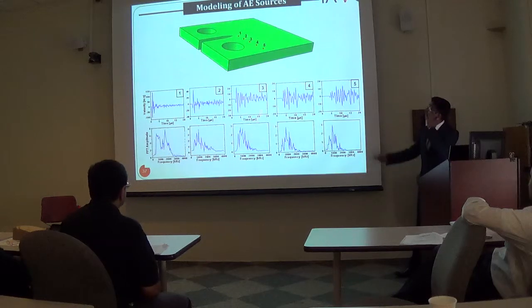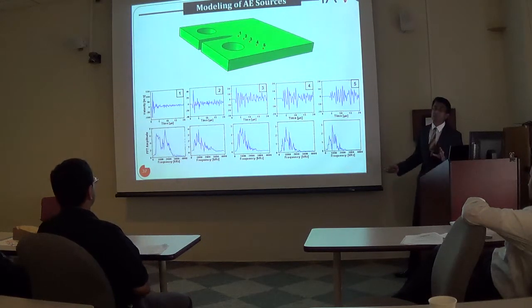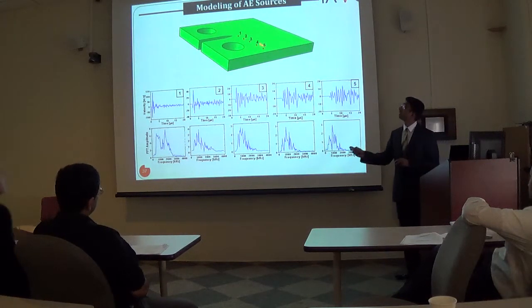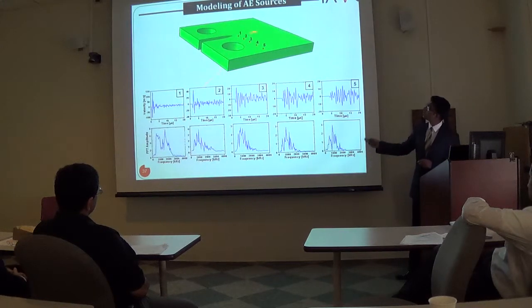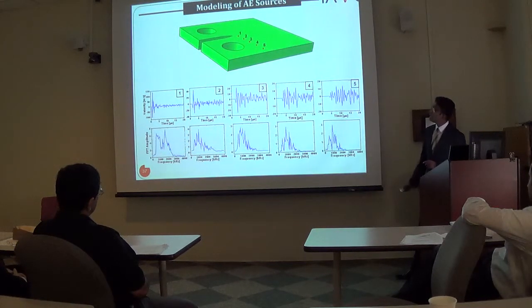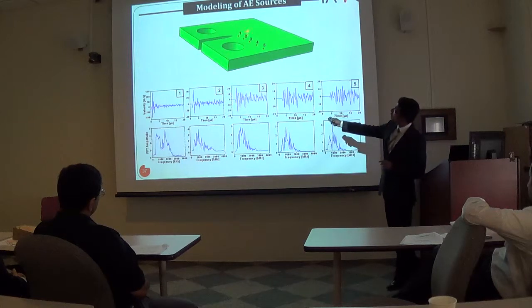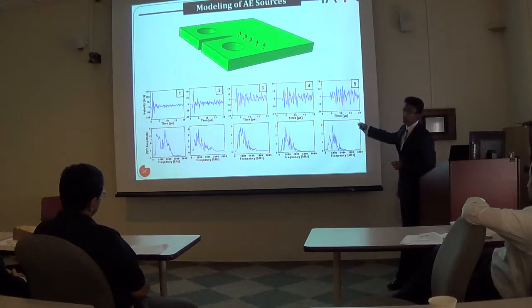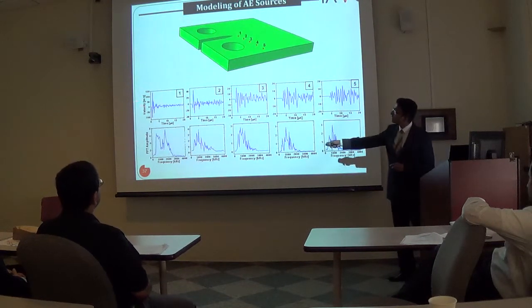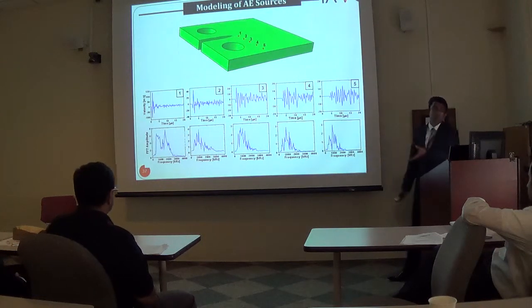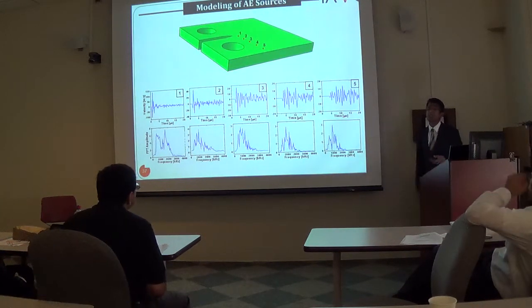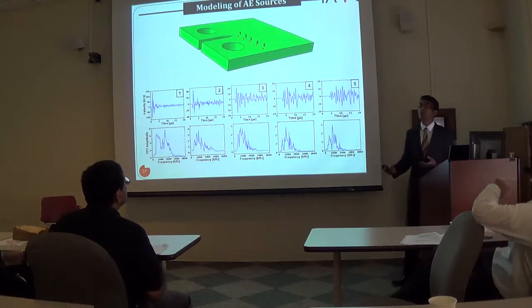So in order to understand how the waves propagate in the material, 5 different virtual AE sensors were placed on the CT specimen, and the waveforms corresponding to the 5 locations are shown here. It can be seen that the initial amplitude that was picked up close to the source seemed to decrease as it propagates in the material, and the time of arrival is also seen to increase as it propagates. Now, this is very important to understand how to place sensors and how to understand what the final sensor waveform would look like.